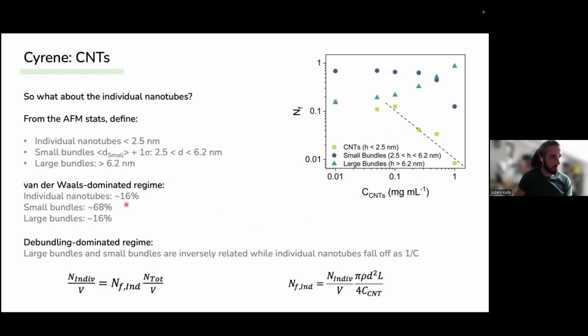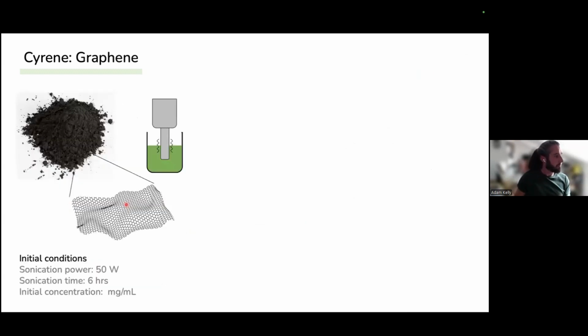So the take-home message here for the carbon nanotube exfoliation is that we're producing, in Cyrene, individual nanotubes at a yield of about 16%. So if we move on now to graphene, once again, we're going to take initial conditions that are common to exfoliating powdered materials using this liquid phase exfoliation process. This time, even though we know we're going to be converting and creating the self-aldol condensation, we're still just going to go ahead and do it anyway.